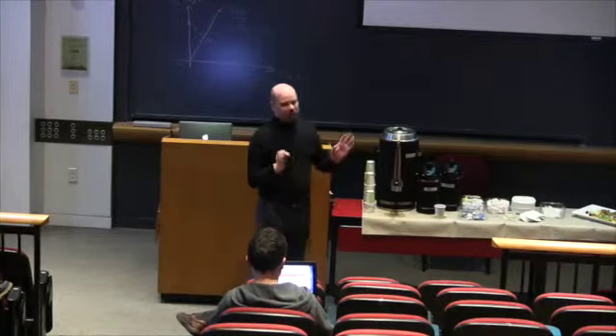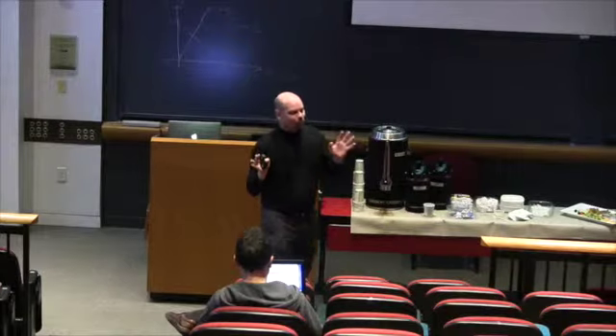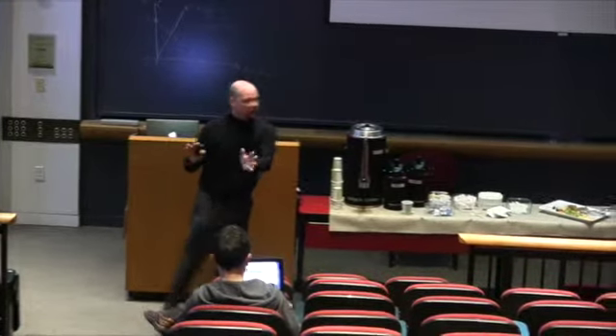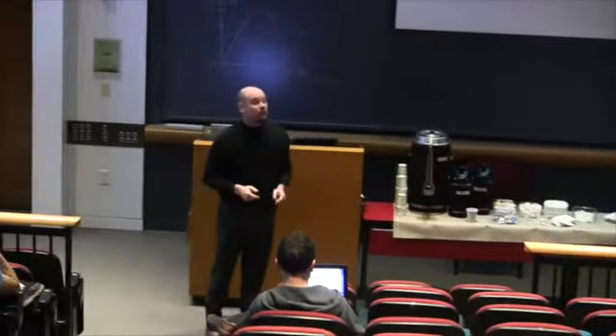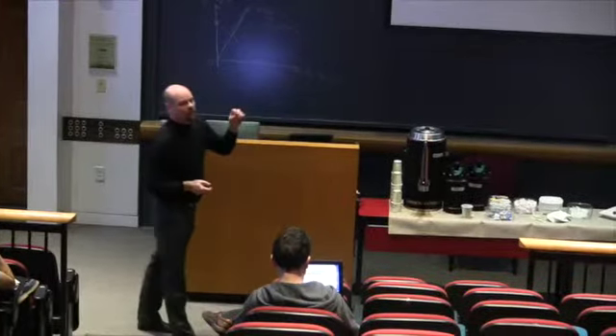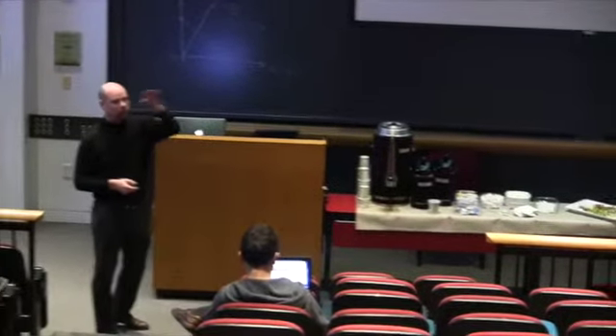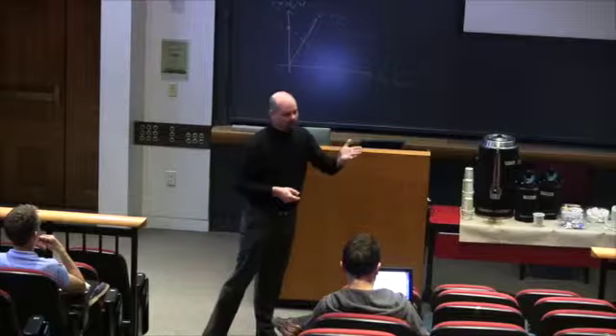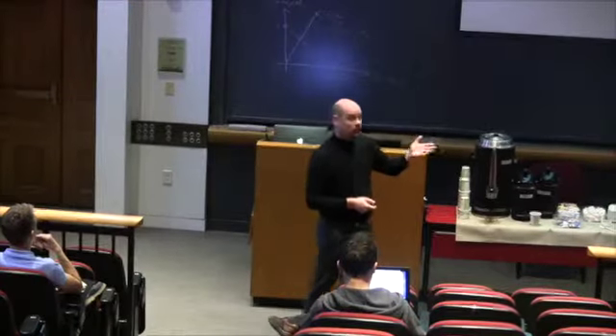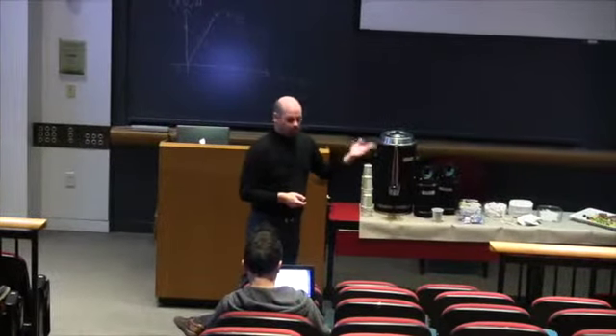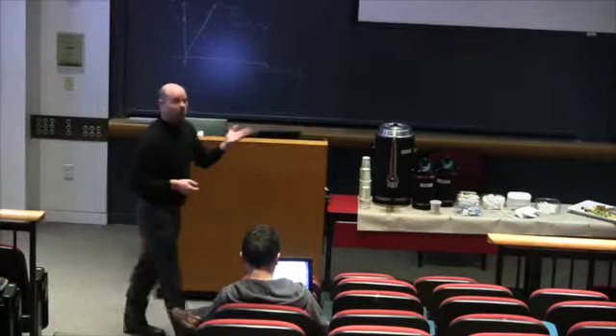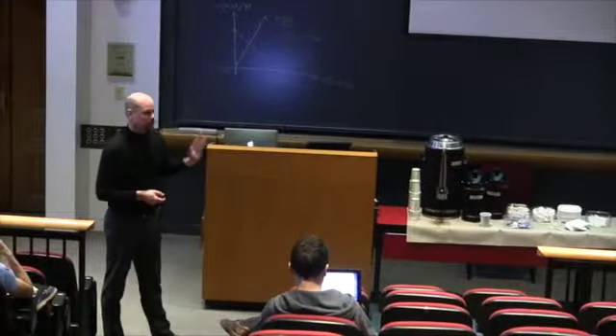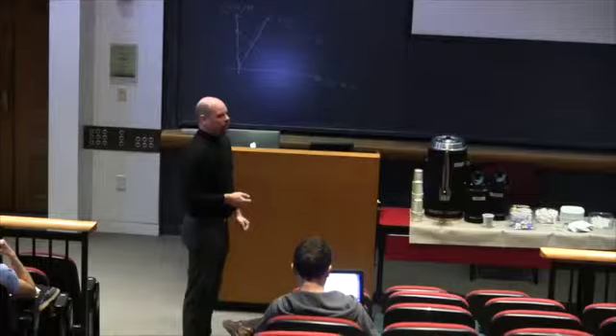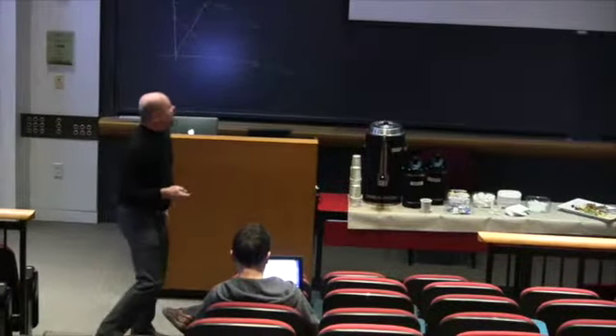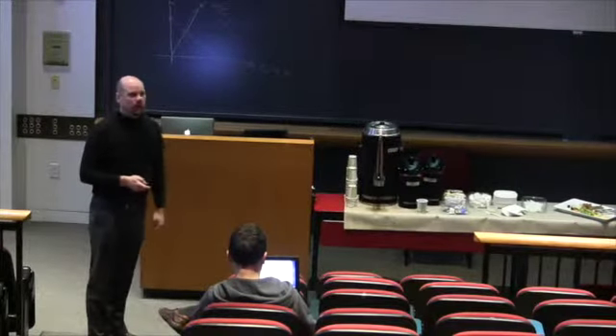And again, that's an argument to put the whole problem aside. The first time that momentum conservation was shown, where one could show that there is a dispersion of the magnons, which we know from neutron scattering, and was also measured by RIXS, people were actually surprised by it. Many people in the community had not appreciated at all that that would be possible. Okay, good. Any more questions?